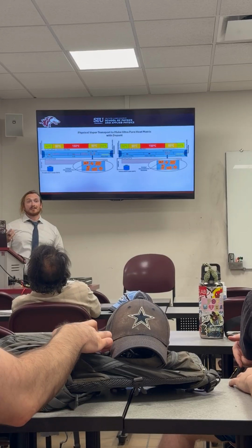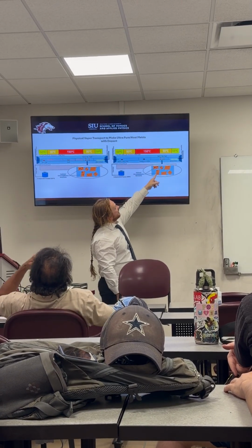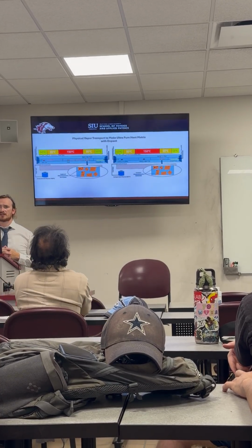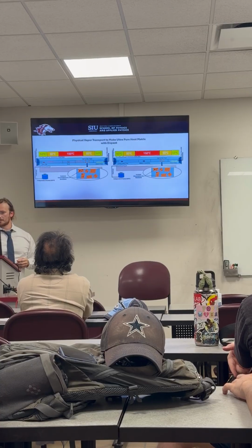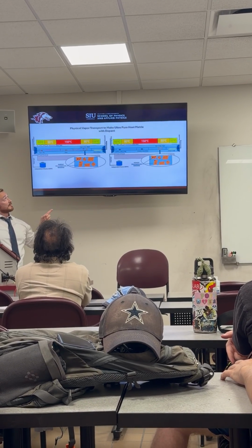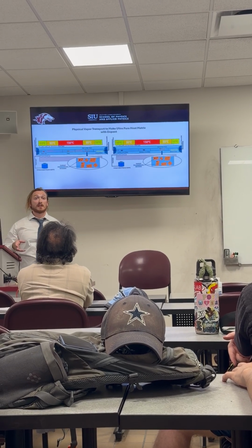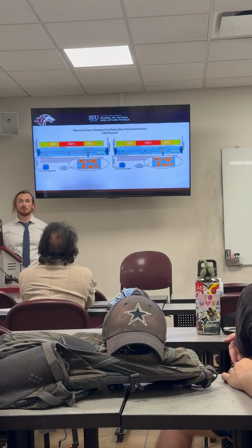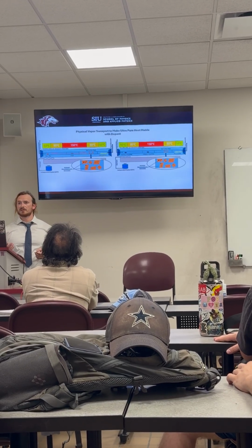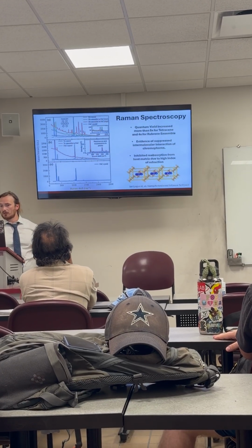And as a secondary benefit to us, we can not only purify the ferrocene, we can purify the chromophore. That'll help with our device characteristics and device emission. After we prepare the samples grown by PVT, at Bumps's lab, we have a cryostation. This cryostation will cool down samples to 10 Kelvin or even 4 Kelvin. We run at 10 Kelvin just to preserve the life of the Montana cryostation. And that will come up later.